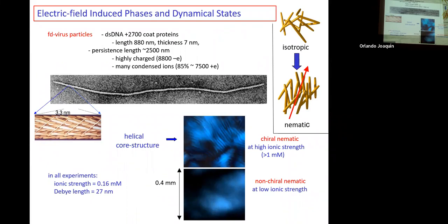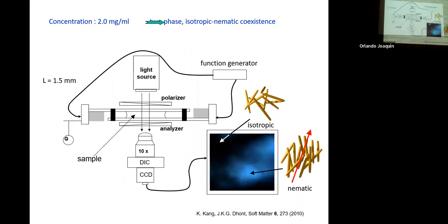Not all the experiments are done at low ion strength, where without the fields, the nematic state is a normal nematic, so a non-cholesteric nematic state. The Debye length is about 27 nanometers, which is much smaller than the thickness of the cell. Okay, so now we are going to apply magnetic fields.